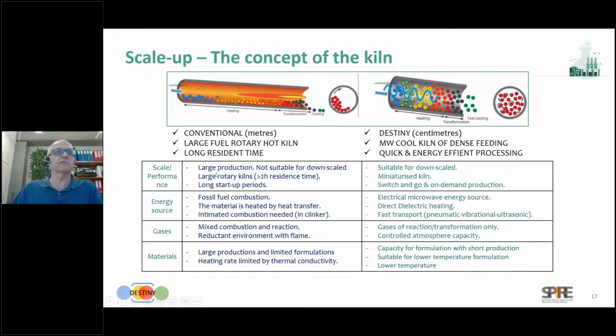I can say just a few words. The conventional kiln is for large production, thousands of tons per hour, and this is not suitable for downscaling, while the microwave is suitable for downscaling, and for flexible production it is much better, and has other advantages. Another relevant thing is the long start-up period that you need for the conventional system, while the microwave is switch and go. So it's quite fast to put in operation, and you don't need preheating or changing things. It's difficult to create, but later it's quite robust.